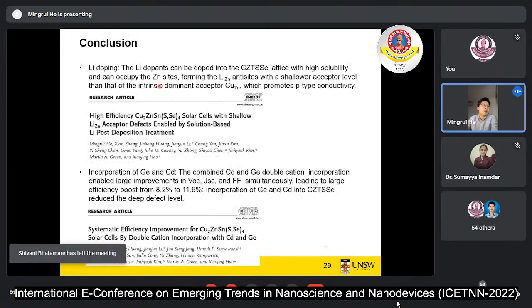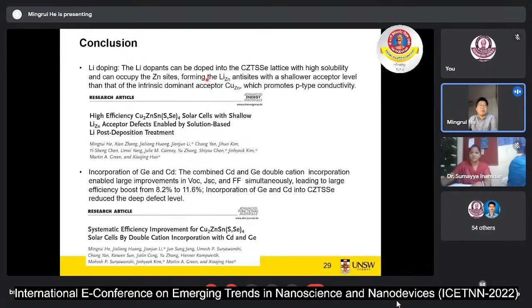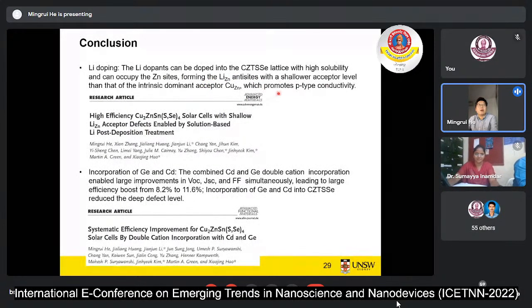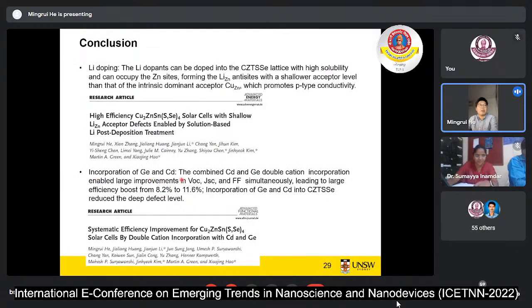So here is the conclusion. The first is lithium doping. We confirm that lithium doping can change the shallow defects, which improves the p-type conductivity, and we published this paper in AEM. Another one is dopant incorporation, germanium and cadmium. Probably you can take a look at this paper in the AFM.